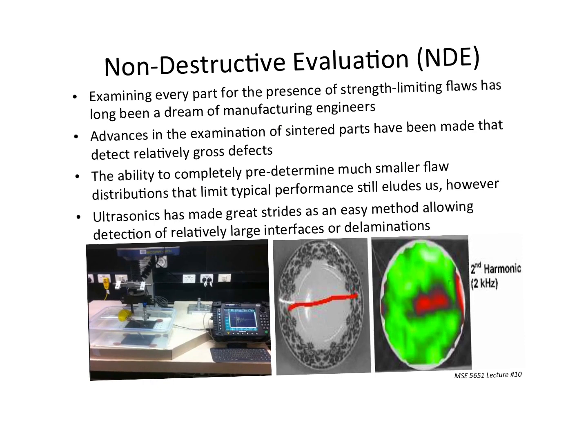And we also do NDE, and there's a bunch of ways of looking at this. You can see relatively large defects, and we talked about X-ray CT. I'll show you that in a second. Ultrasonics is one other technique that's been used, usually only able to see relatively large defects, interfacial defects, but it does work. So Tosoh SMD down in Grove City has one of these things. One of my former graduate students is in charge of it, Jeremy Gomer. And so this can be used to find relatively large flaws.